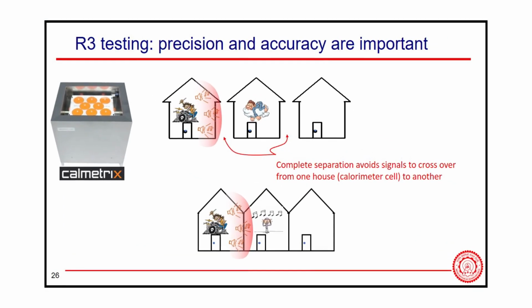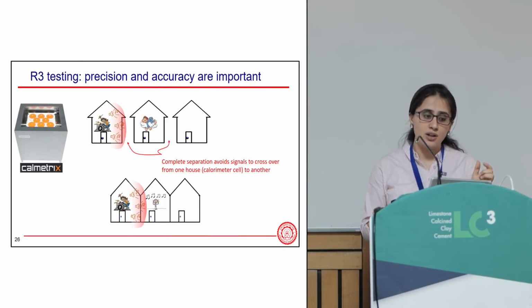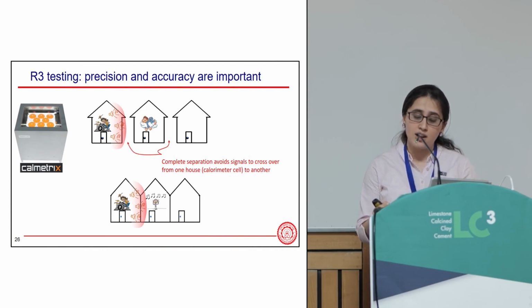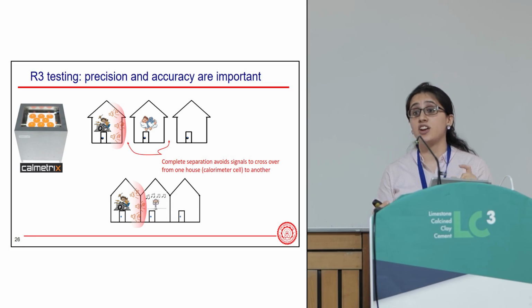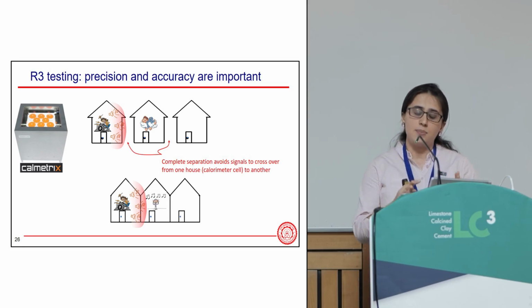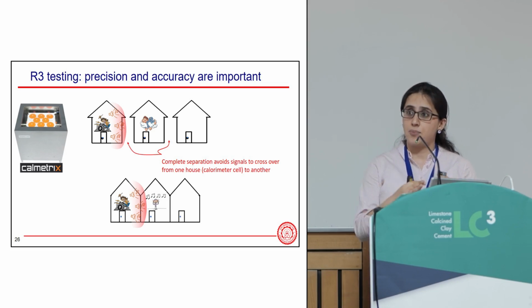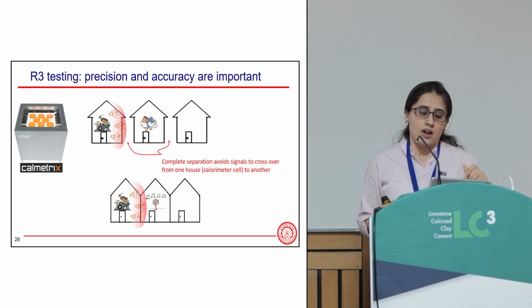So when we are measuring the heat of hydration, we have to be careful that we are actually measuring the heat of reaction that is involved from a particular sample. What I mean is that there are different types of calorimeters available in the market and they have different designs, which can actually affect our results. For example, the calorimeter design should be such that each calorimetric cell is separated, so that we measure the reaction of each sample cell.